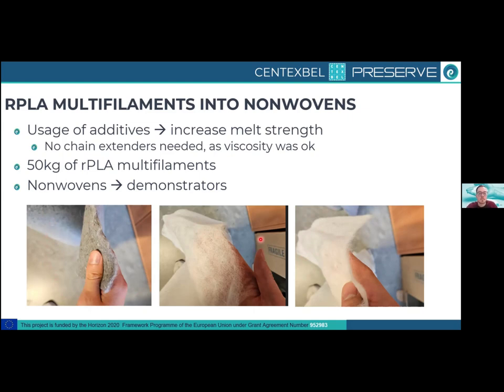RPLA non-wovens. Also to mention, the additives that we have added are checked and are good for biodegradation too. So they have no negative impact. They even have a small positive impact on the biodegradation of the PLA itself.